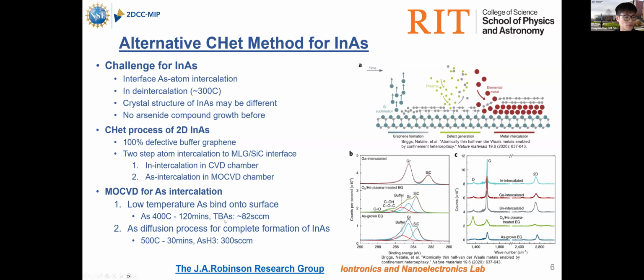So in the first step, we use TBAs as the arsenic precursor, because it has a low decomposition temperature. After we have the intercalated indium sample, a lower temperature will reduce the chance that it will deintercalate. That's the motivation for this step. And during this process, we keep a max flow of arsenic to ensure that the arsenic atoms are bombarding the substrate instead of diffusing away from it.